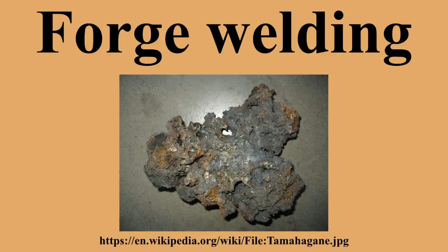By the end of a blacksmithing job, the steel will be of a lower carbon content than it was prior to heating. Therefore, most blacksmithing operations are done as quickly as possible to reduce decarburization, preventing the steel from becoming too soft, to produce the right amount of hardness in the finished product. The smith generally begins with steel that has a carbon content that is higher than desired. In ancient times, forging often began with steel that had a carbon content much too high for normal use.